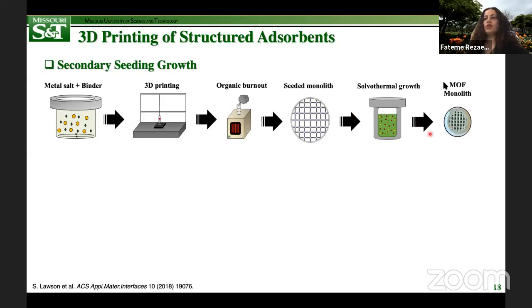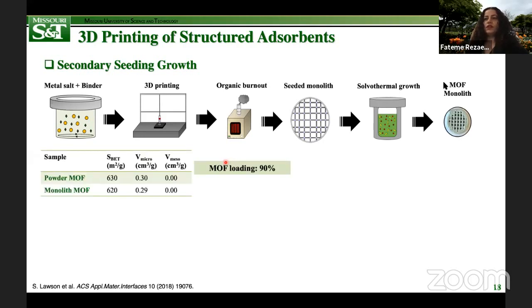The metal weight loading in the binder support could be varied systematically to optimize the MOF growth while retaining the mechanical integrity of the final structure. This is the most noticeable advantage of secondary seeding growth. So here, the obtained UTSA monolith with the 90% loading exhibited similar textural features while improving upon mechanical strength. Using this technique, we managed to obtain MOF loading of around 90 weight%.